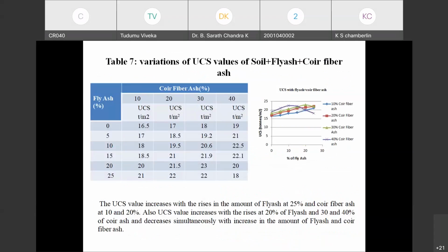And next one is the variation of the UCS of the soil plus fly ash plus coir fiber ash with the different percentages. From this graph, the UCS value increases with the rise in the amount of fly ash at 25% and coir fiber ash at 10 and 20%. And the value increases with rise at 20% of the fly ash and 30 and 40% of the coir ash, and it decreases simultaneously with increasing amount of the additives.